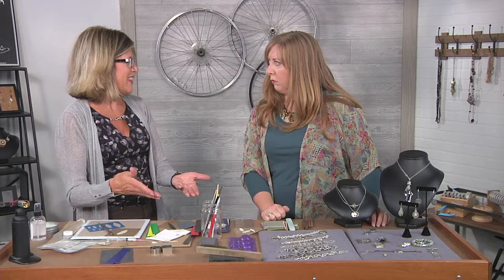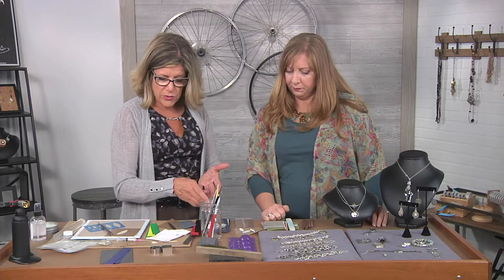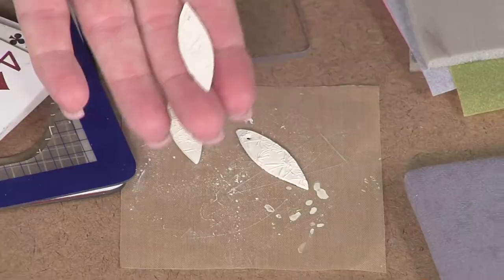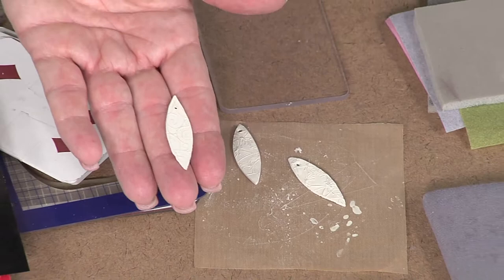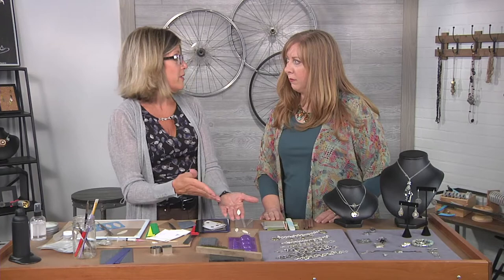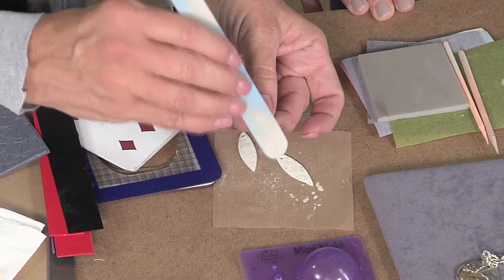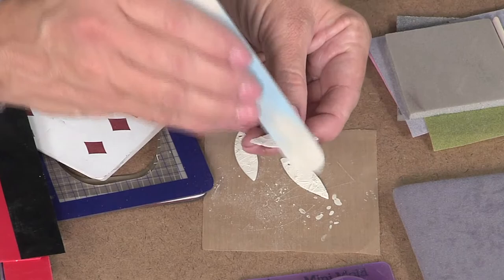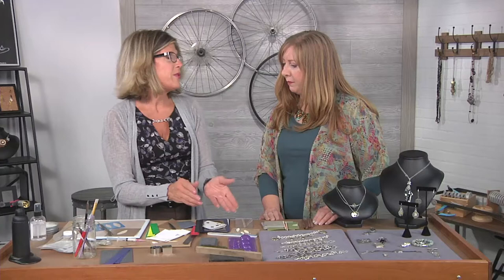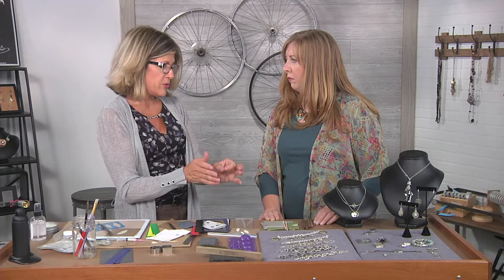With every stage I like to do as much cleaning up as possible — there's less waste and I can keep it more in its original lump form. Once the piece is cut out you refine it, using a range of filing abrasives. Similar to woodworking, you go through a progression of grits to make the finish smoother and smoother — and this is all done before firing while it's still clay. The more you clean it before you fire it, the better it comes out. You can fire it in a kiln or with a butane torch; the kiln is the optimum choice, but the torch works for pieces smaller than a half dollar if needed.